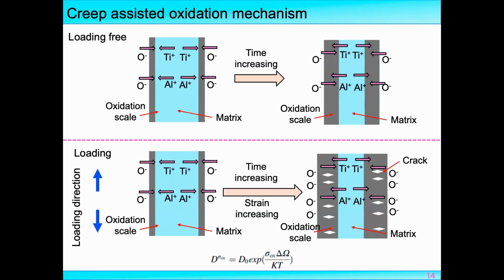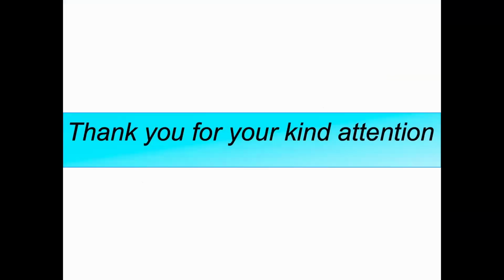However, if it is tested under creep loading, at the early stage the mechanism is almost the same. However, with the increase of testing time and the strain increasing, so many microcracks were formed in the oxide scale, so much more oxygen ion can pass through this layer to react with the titanium and aluminum ion. Therefore, the thickness of this oxidation layer is higher than that one. Okay, the conclusion. Thank you for your attention.